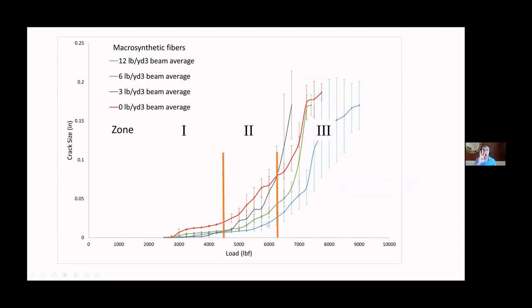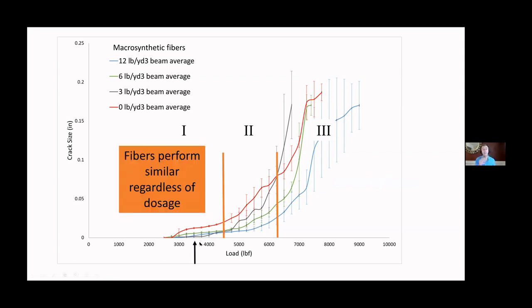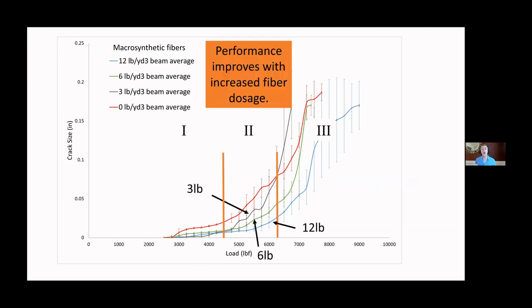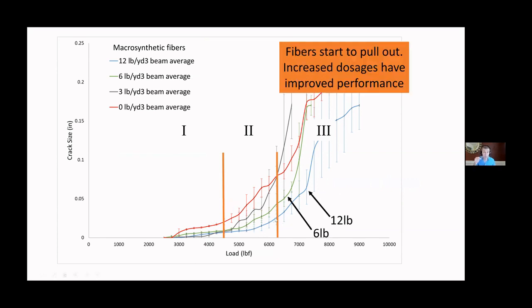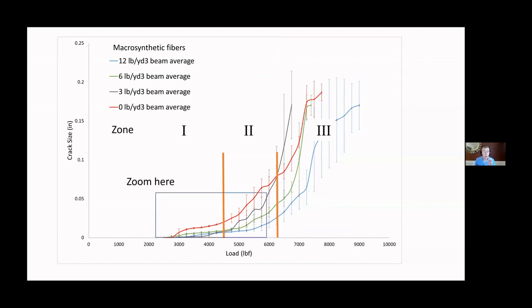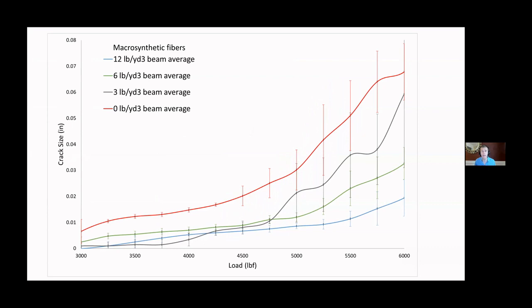There are actually 3 zones of behavior in fiber reinforced concrete. In zone number 1, the fiber dosages all perform fairly similar to one another. They keep the cracks smaller, and we'll talk more about that coming up. In zone number 2, the performance improves with increasing fiber dosages. And then in zone number 3, the fibers start to debond and pull out. This is a little bit different for steel fibers. So again, we're talking about macrosynthetic fibers today. It's pretty cool. But we care about zone 1 and zone 2 for the most part, for durability, keeping those cracks small. So let's zoom way in here, and I'm just going to pick a crack.